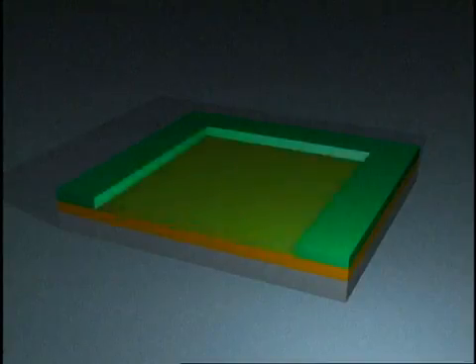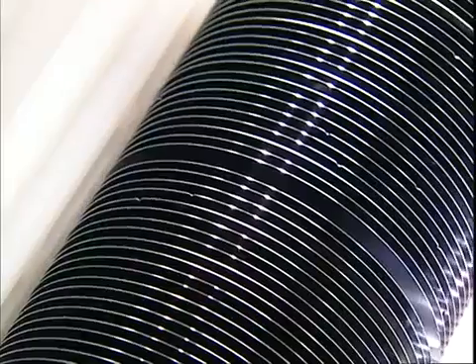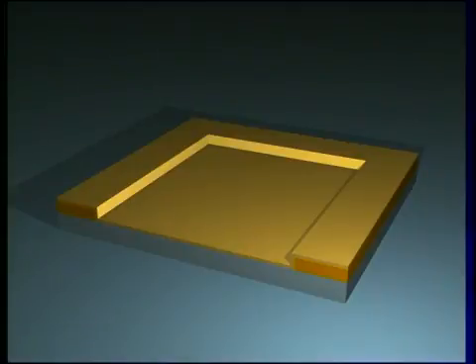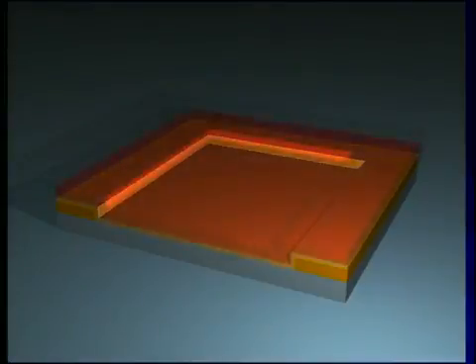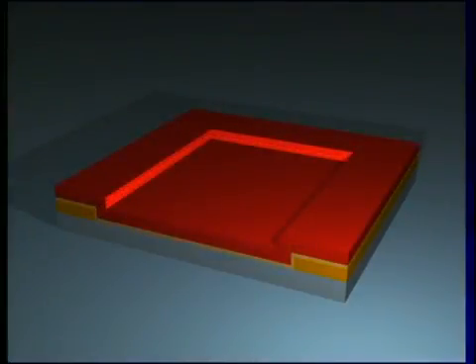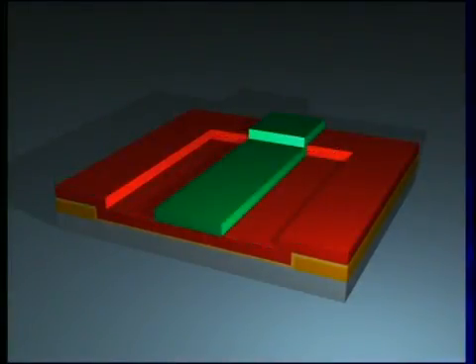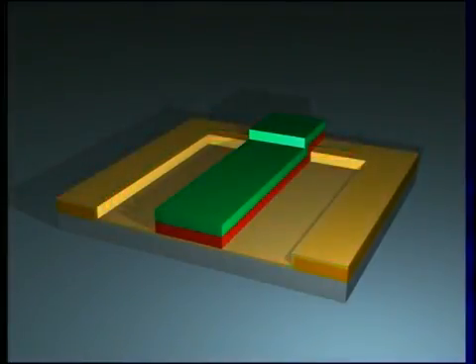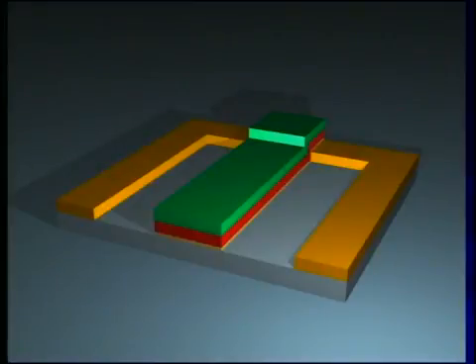The exposed section can be developed, while the unexposed feature remains. The oxide layer is etched off. This etching process is carried out either by wet etching or plasma etching. In plasma etching, special gases combine with the layer to be removed, making it possible to remove the microscopically thin layers inside the windows created by exposure, development and etching. After dissolving the remaining photoresist and cleansing, another oxidation takes place — this time, a very thin layer is affected. Electrically conductive polysilicon is deposited on this insulation layer. Then, once again, photoresist, mask and exposure occur, and the exposed photoresist is again dissolved.